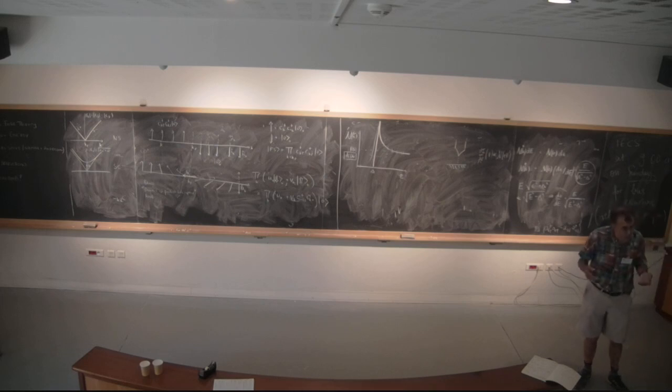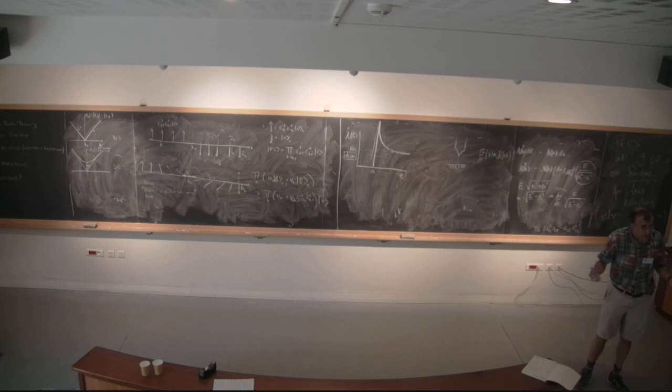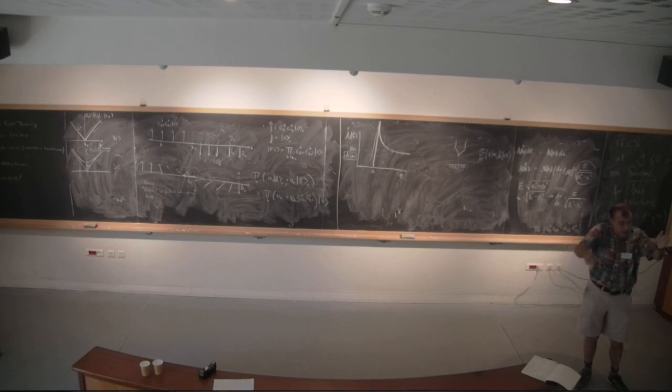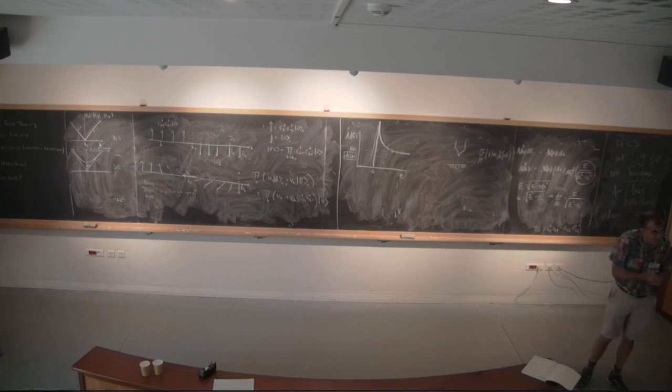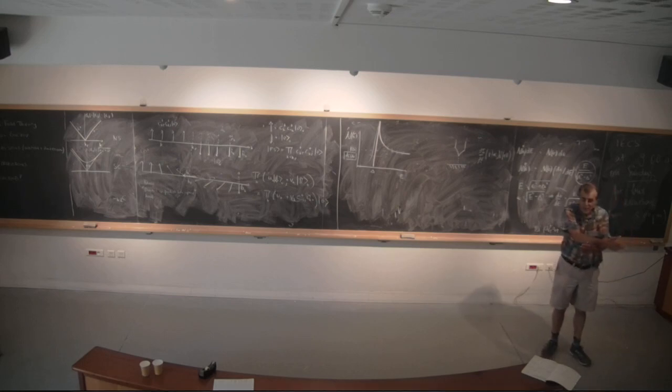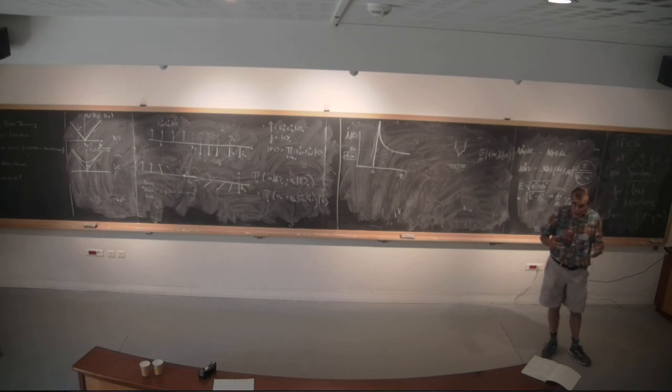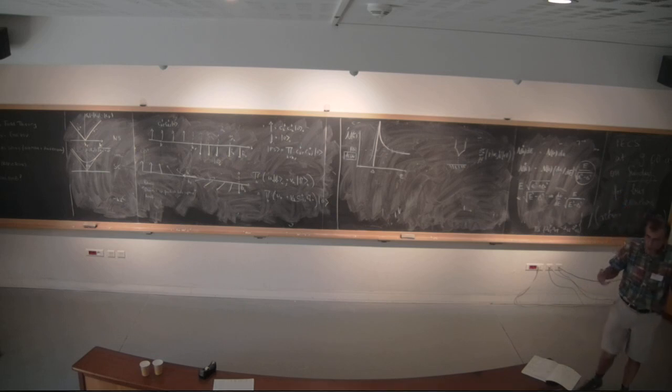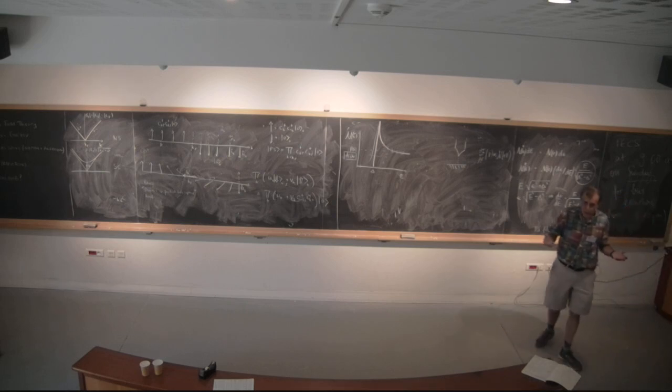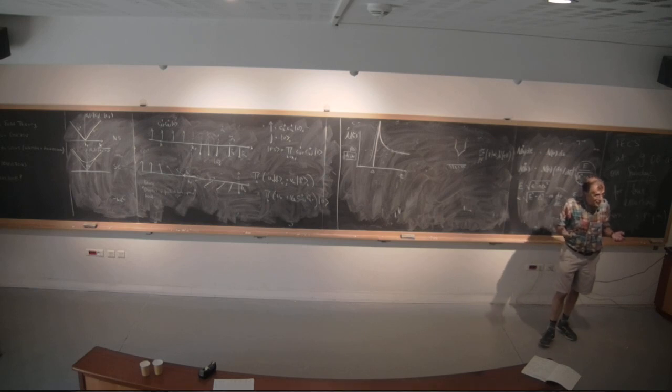It has to introduce nodes into the condensate somewhere. In BCS theory, that node is at finite energy. So the gap function actually changes sign as you go out to high energies to compensate for the fact that the interactions are repulsive at high frequencies and attractive at low frequencies. In high-temperature superconductors, the gap changes sign in momentum space in cuprate superconductors. We don't know where the node lies in the iron-based superconductors. We thought we understood the nodes of strontium ruthenate, but we're having to revise our understanding there too.